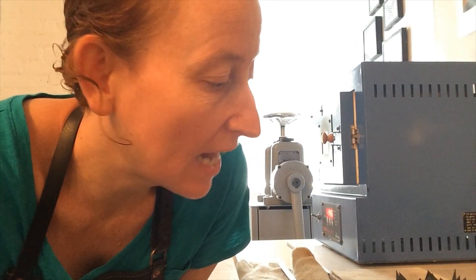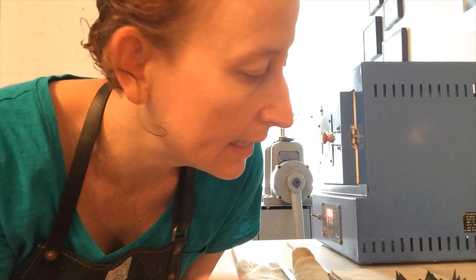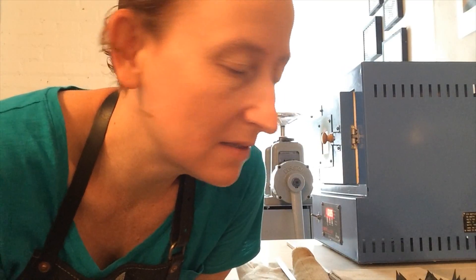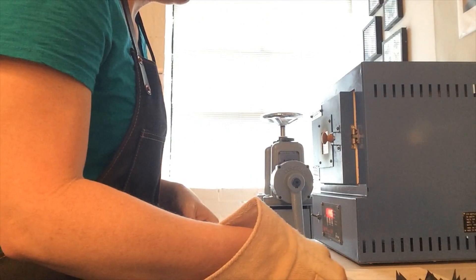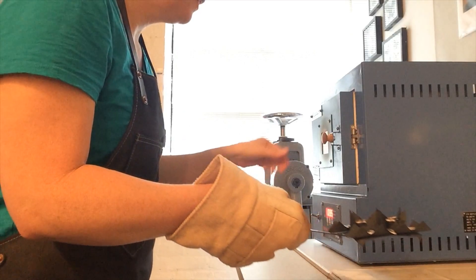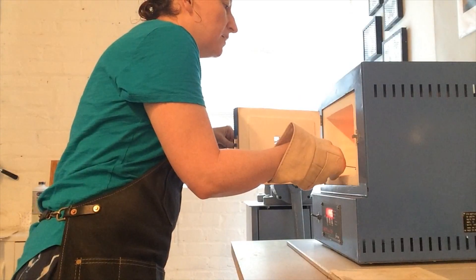It's me again. We're in front of the kiln right now, which is very exciting. I have finished all these pieces — I've polished them with all the sandpapers, and then I washed them with soapy water and rinsed them in distilled water so they were nice and clean. And I'm going to do something called the final fire polish right now, which is basically putting them back in the kiln and remelting the glass. You can load up as many as you want — it's really a matter of comfort level for how many pieces you want to put in.